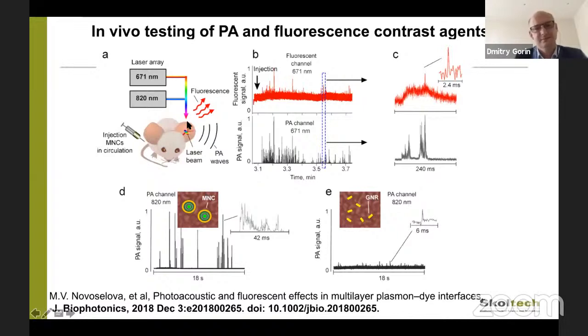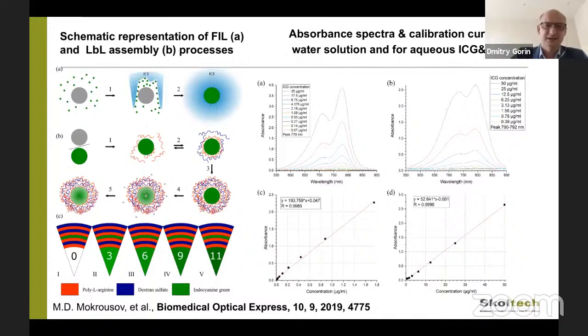And we injected these probes into a mouse, and we obtained both fluorescence signal and photoacoustic signals. And we compared the optoacoustic signal from our particles with the optoacoustic signals obtained from gold nanorods. And we obtained the highest signal because we have a big object, a bigger volume, and enough chromophores that can absorb light. But our colleagues, our medical doctors, asked us about excluding any inorganic nanoparticles from our structure, and we tried to think how we can prepare a bimodal contrast agent using only a fluorescent dye, the FDA-approved fluorescence dye indocyanine green.